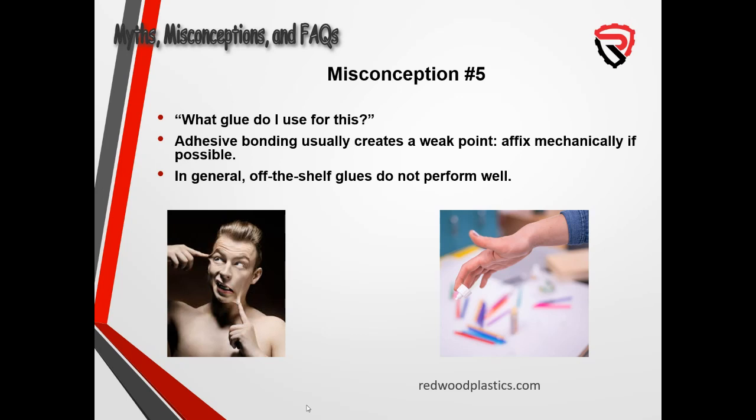And we say here, nothing sticks to UHMW. There's no adhesive or glue that's going to work well at all for that. So the answer is to affix mechanically, if at all possible. We would tell you it's really your only choice. And sometimes customers will say to me, well, you know, Matt, I don't want to drill a bolt through my hopper to attach your UHMW. And I go, well, you don't have to. There's a solution for that. We have something called a weld washer, which is you don't need a drill. You just have a counterbore hole, stick in a weld washer, you weld in the center, you put on a cap, you're done. And there's no drilling. So there are mechanical solutions for many applications, but in general, adhesives and glues don't work.